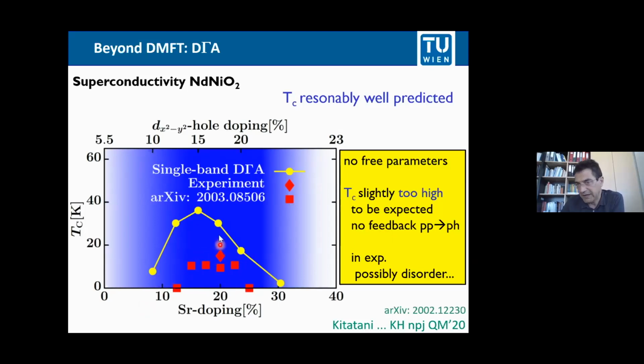And considering that we overestimated TC from the beginning, I think that's a very good prediction of the TC. In the cuprate, in the nickelates, if we had adjusted the U, as I mentioned before, for a larger U, that point would have been here, and we would have been on top of the experiment. Still, I think that is an error cancellation. The U is not so much bigger than we have found here.